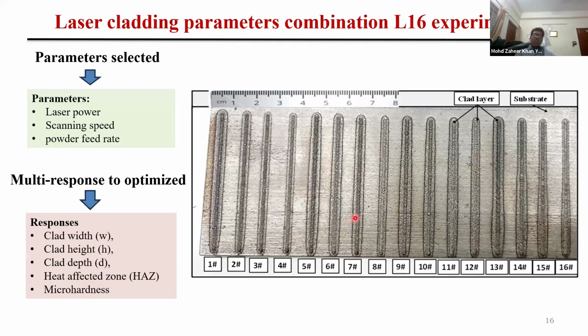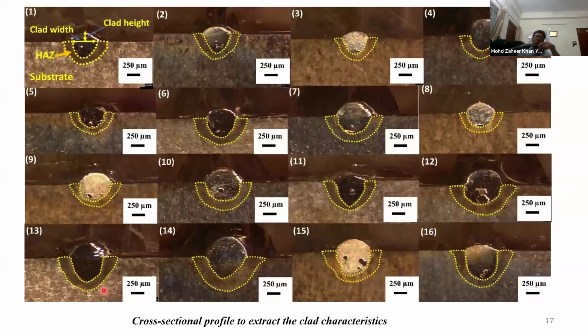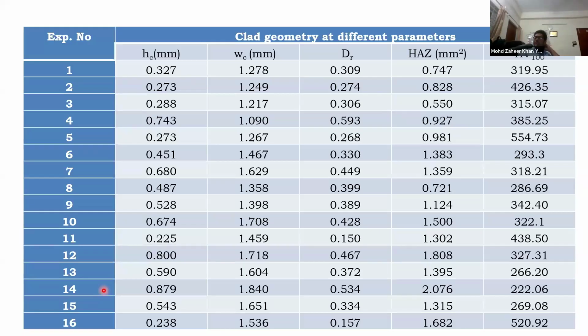In this particular experiment, one of the students performed this experiment and deposited a single layer of clad in 16 different combinations of laser power, scan speed, and powder feed rate. And then these clad width, clad height, clad depth, heat affected zone thickness, and microhardness. And apart from this, the dilution was calculated as this. So all these plates were actually cut across, and the measurements of clad width, clad height, dilution, and the thickness of the heat affected zone were measured, and after measuring, it has been tabulated like this.